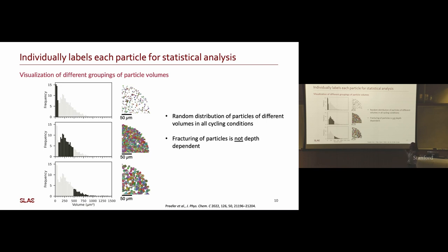We actually found no dependence on depth for the fracturing of the particles. So they're very randomly distributed. So this was a null result: we thought it might happen, but actually the cracking and the fracturing is happening uniformly throughout the depth of the electrode, which is a good thing. It means we're utilizing the full cathode.